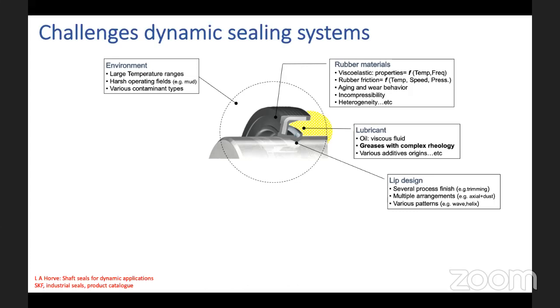And then the design also plays an important role. In this rotary lip seal, you can design your lip for low friction, in such a way that the area of real contact is a bit less, but at the same time not compromise on the leakage. And then you can have different patterns of seals, wave and helix, and different arrangements of these seals. And the surface is also very important. The shaft on which the rotary lip seal is sitting can have different finishes, and that will also affect the properties.